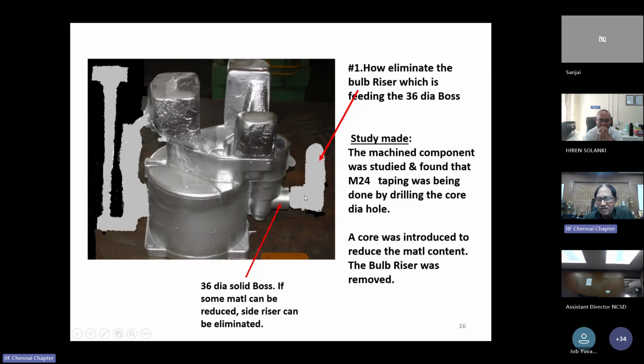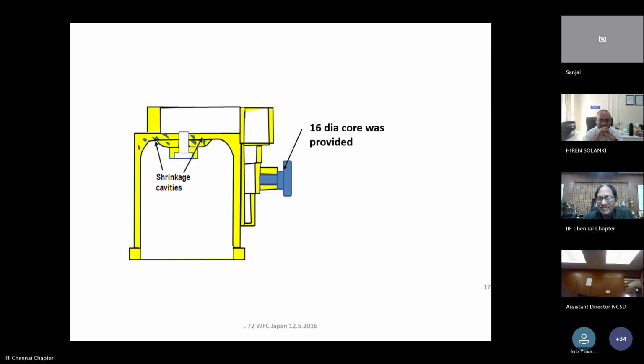One of the fundamental approaches for shrinkage is, number one, explore the possibility of reducing the wall thickness of the casting material if the design permits. This is the first step to be followed for solving any shrinkage problem. Luckily, we have this 36 dia being tapped to M24. So a 16 dia core was newly introduced in the die, and nearly so much length of material has been removed.